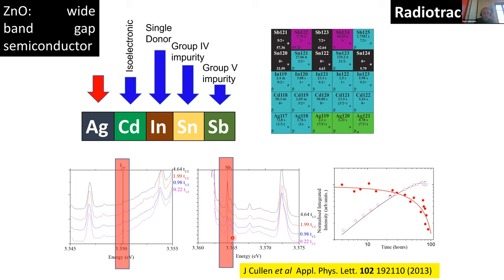You can see the decay of a very weak line decaying with a half-life characteristic of tin-121, and the growth of a new feature related to the daughter isotope of antimony, which is stable and you can see it growing in. This featured in Applied Physics Letters seven years ago. We hope now to reactivate this activity for studying sensors in diamond.